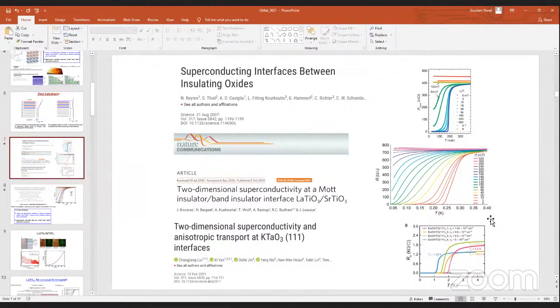I'm not trying to pick holes in the theory, but I was trying to make a similar comment: if it is coming from STO, then why do we not see the superconducting phase on all materials deposited on STO, number one, and why does the entire STO substrate not become superconducting? It may come from delta doped STO, but it is confined at the interface, and we essentially have a 2-dimensional superconductor which is interplaying with magnetism.